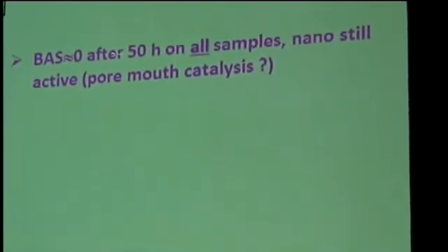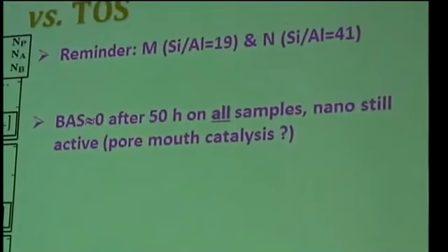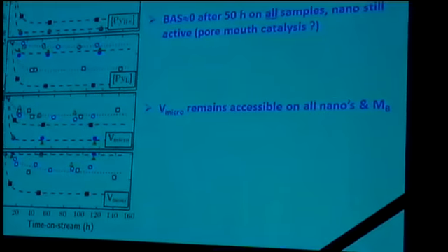The number of Brønsted acid sites goes down to zero after 50 hours for all the samples. We do not know if it's pore poisoning or pore plugging, but we know that these materials are active after having almost no Brønsted acid sites. So most probably, but we are not yet sure, there should be some kind of pore mouth catalysis, where coke deposits on the surface and the catalyst keeps working, and we do not see any more pore volume. Again, only on the nano-sized material some micropore volume remains.